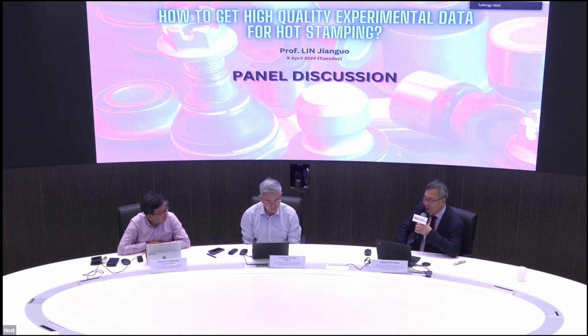And there are two reasons. One is we planned to do this work, but it has not been done yet. And secondly, we did a lot of tests for non-linear strain paths, but with a linear strain path, we get the minimum ductility of material, the lowest fracture limit curves. That's the most conservative way to predict. If we can satisfy this, all other conditions would be okay.